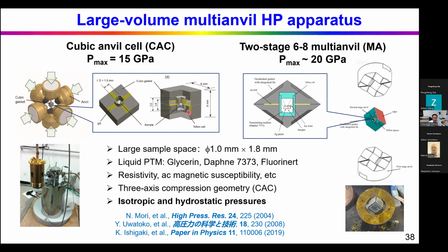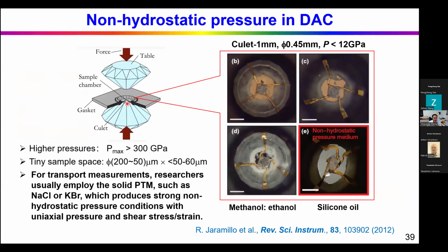And for both techniques, the sample space is pretty large. The inner diameter is about 1 millimeter, and the length of the Teflon capsule is about 1.8 millimeter. So it's at least 2 or 3 orders bigger space than the diamond anvil cell. In comparison, for the diamond anvil cell, the sample space is very tiny. Normally the hole size is around 100 micrometer, and the depth of this hole is about 50 to 60 micrometer or even smaller.